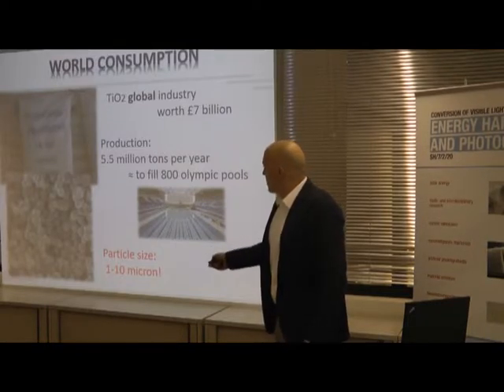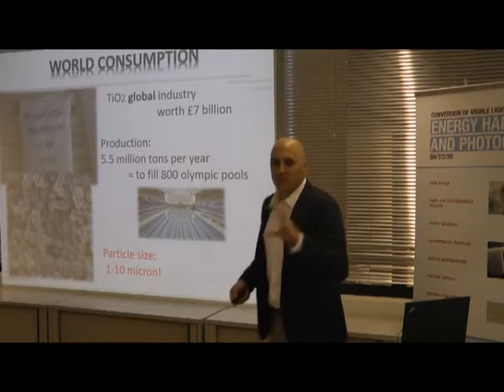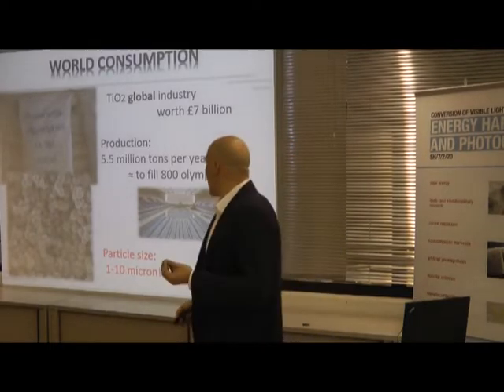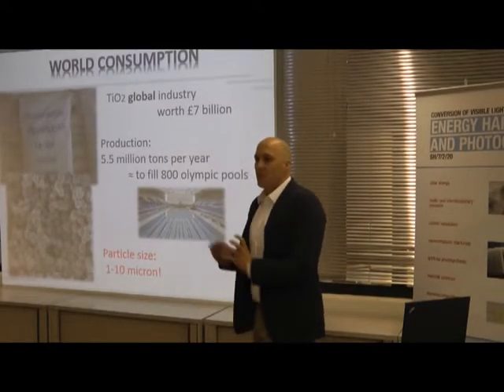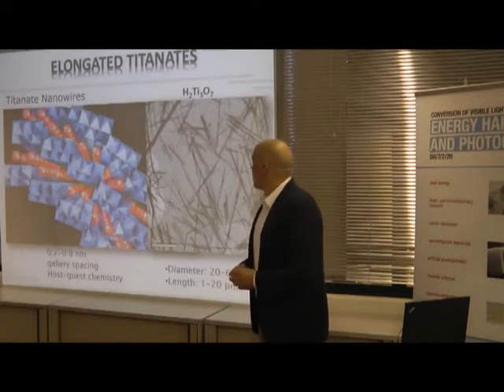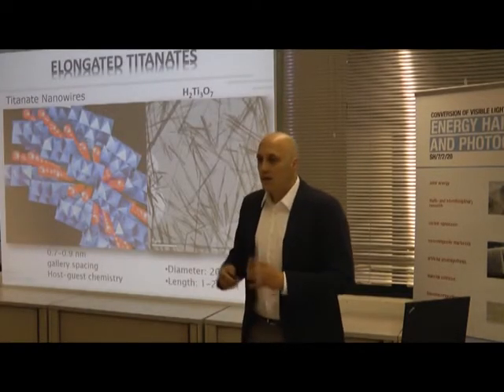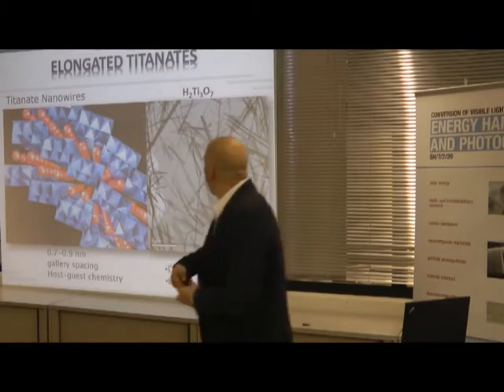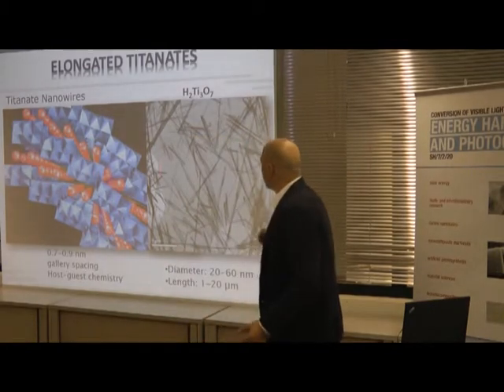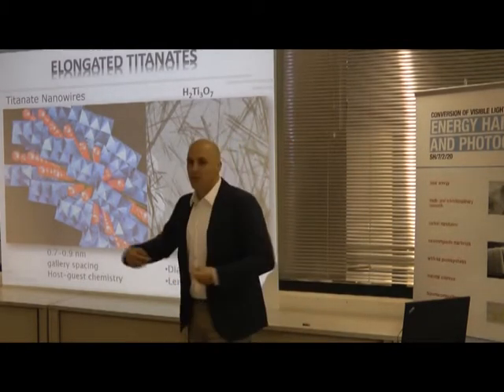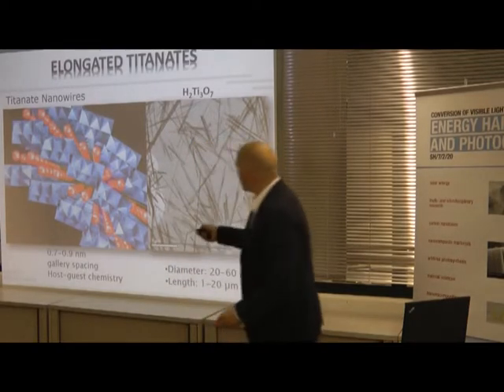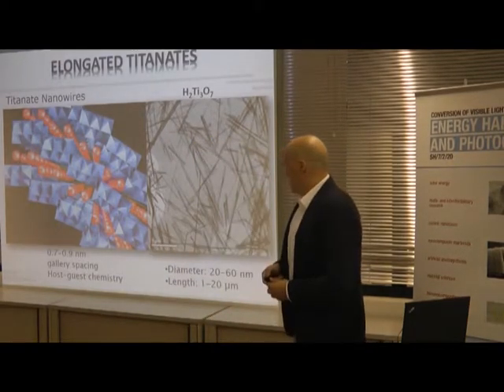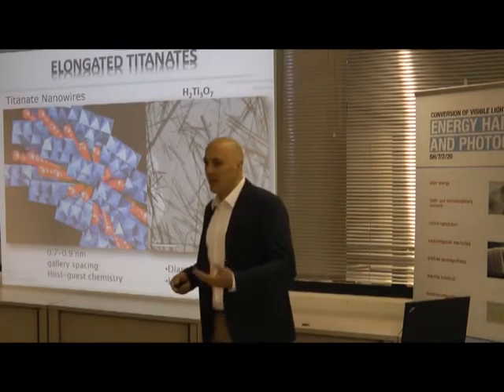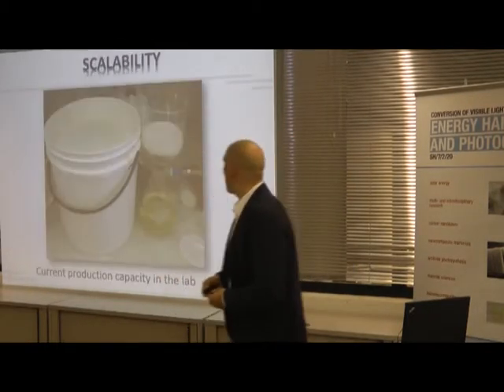And I would like to outline that the particle size of this compound, this powder, is micron size, and it's spherical. So what we are producing in the laboratory is not spherical, but elongated. So we are producing titanium nanowires, the elongated version of this compound. It has a special layer structure, which we can use later for doping, and I will show you how.